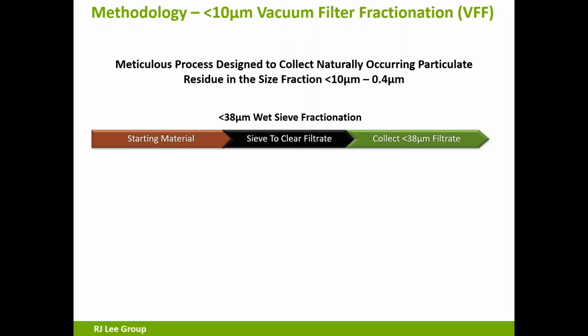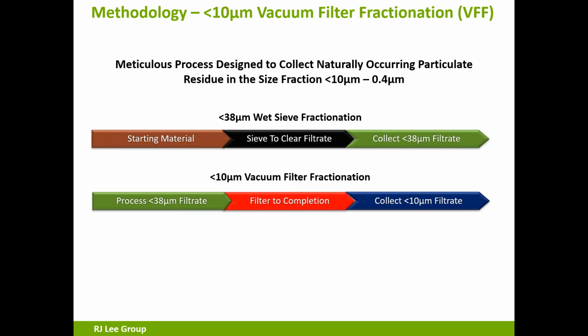It starts with a 38 micron wet sieve fractionation where we simply bathe the material over and over. Sometimes this can take days to get all of the particles to stop passing through. We continue the 38 wet sieve fractionation, just washing the material down until we do not see any particles by eye under light and white paper coming off. We then stop, collect the less than 38 filtrate, and run it through a 10 micron filter. This is just carefully processed. We start with a very small amount of material, 0.5 grams, so that it coats that filter nice and evenly.